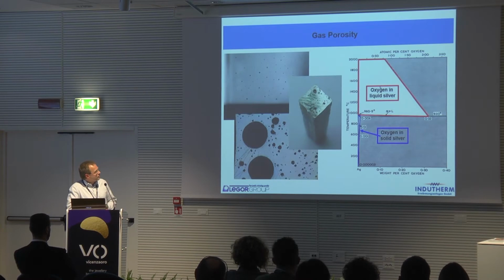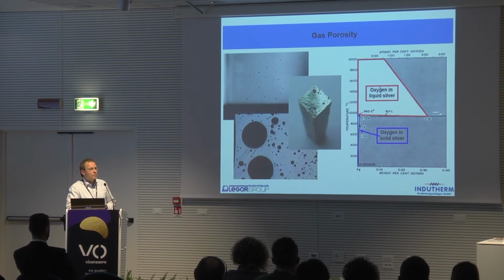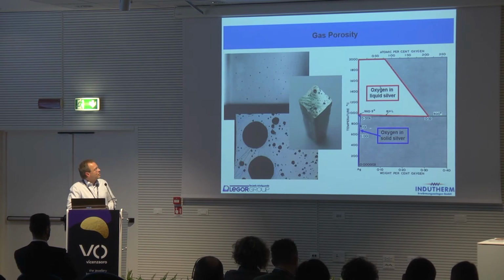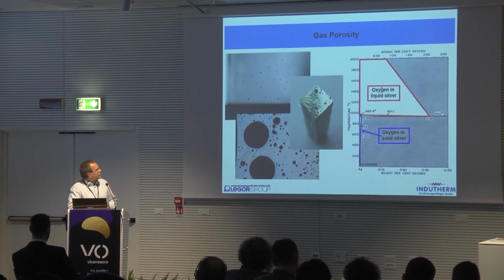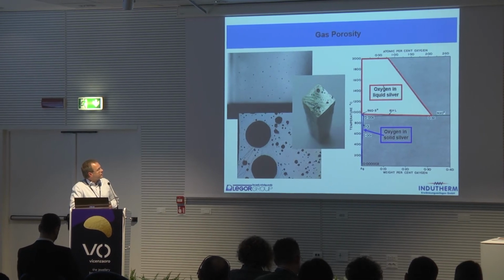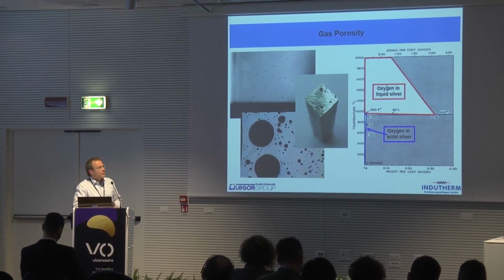As opposed to that, when the metal solidifies, this small area indicates the small amount of oxygen that we can dissolve in the solidified metal. So what is happening with the oxygen when the metal solidifies? You can see it on this ingot here. The gas tries to escape, and we form typically spherical gas pores.